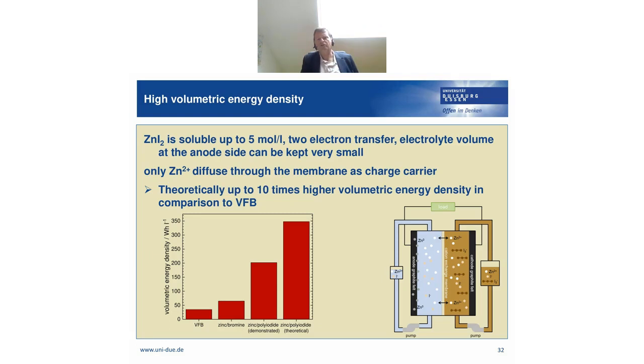We have a 2 electron transfer. In the case of vanadium, we have a 1 electron transfer. And the electrolyte volume at the anode side can be kept very small. So we see here again in the bottom right picture the cell, and you see that the tank for the electrolyte on the anode side is drawn much smaller. So this is to visualize that the electrolyte volume at the anode side can in principle be kept much smaller. And as I've said, only the zinc ions diffuse through the membrane and they act as a charge carrier.